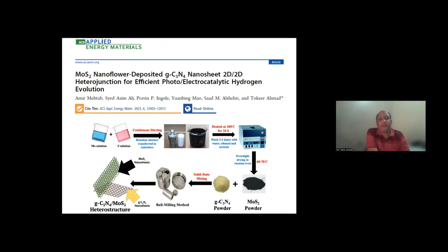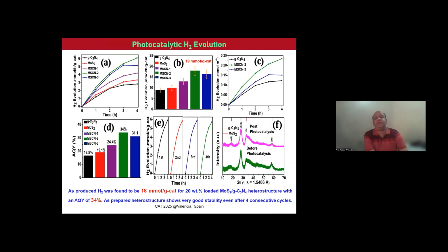And then these are the MoS2 nanoflowers that we have made with the help of the hydrothermal method. Then by mechanical mixing, they were mixed with the graphite carbon nitride to make the 10, 20, and 30% ratio of the MoS2 with graphite carbon nitride binary heterostructures. And this is the synthesis protocol, how we have formed these beautiful nanoflowers of the MoS2 with the graphite carbon nitride. And here the 20% loading of the MoS2 on graphite carbon nitride is able to produce 18 millimole per hour per gram of hydrogen with an apparent quantum yield of